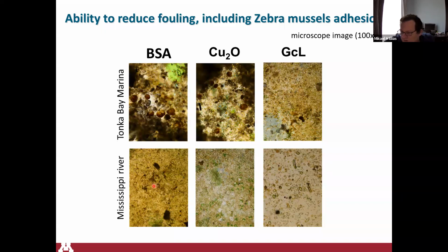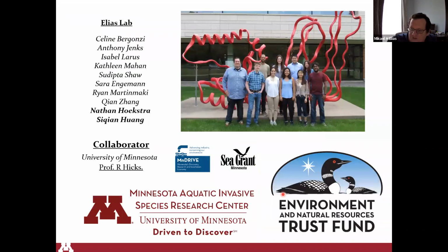And you see a different pattern in the Mississippi River. Again, we didn't see many zebras there over the summer, but you see that there is a lot less material on the treatment. And interestingly enough, what you see is that you have a little more and bigger diatoms with this treatment. You have a lot less material on the surface, but you have a little more and little bigger diatoms. So this is something that we're currently investigating.